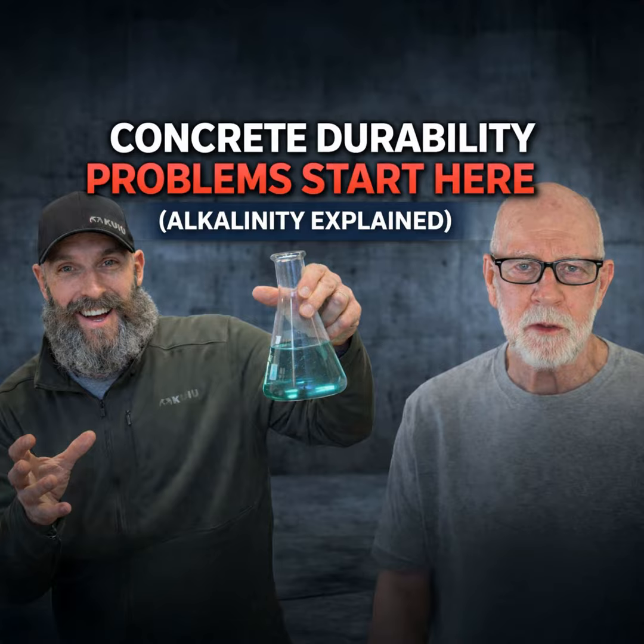That's where we're getting into the sodium hydroxide. That's the bad guy. That will start capturing water at 9% relative humidity. Even if it's desert dry, it can get wet and stay wet in really, really low humidity environments. And that's what's in the concrete, and that's what's interfering with the top surface of the concrete.